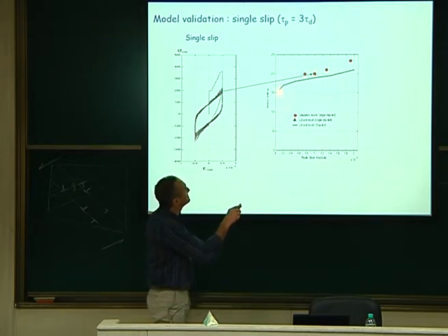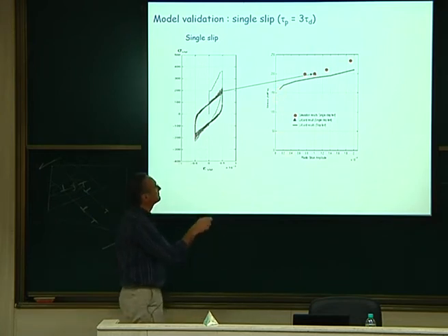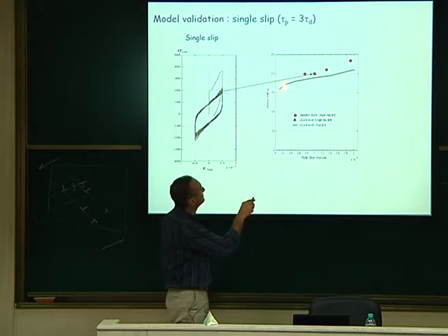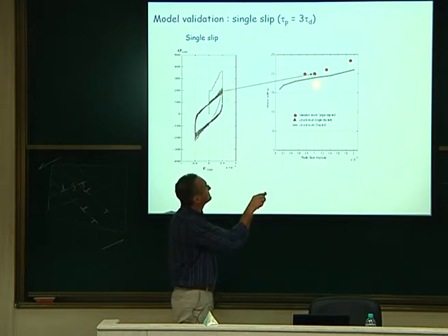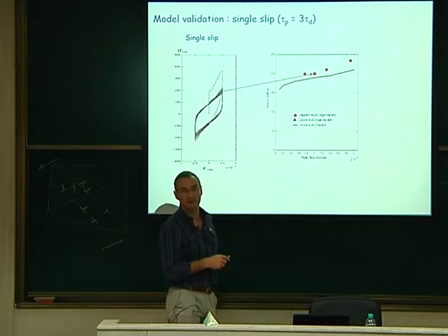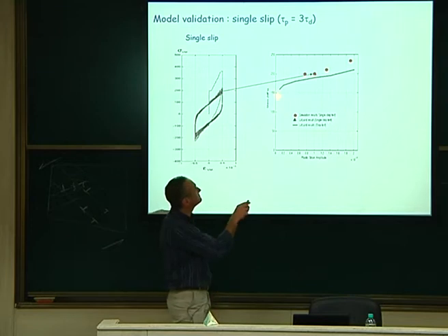So it means either you start with this amount of fatigue plastic strain, or like this. If you increase slowly your plastic strain amplitude, you will follow this stress level, the saturation stress level. If now you start from the beginning at this amplitude, you will get a stress a little bit higher. Okay? That's experiments. Today we are just doing the same curve as this.